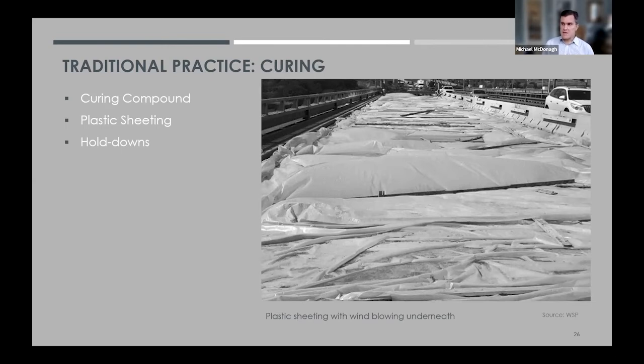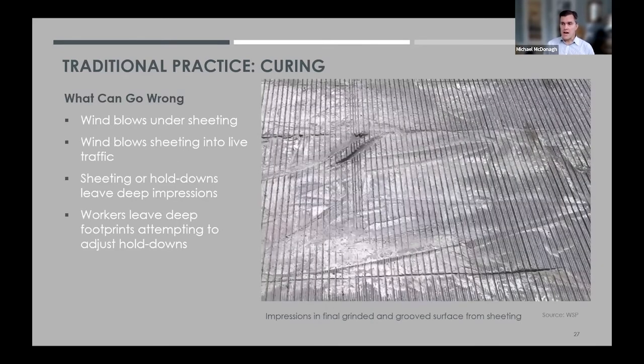The plastic sheeting needs to be held down, and that has to be carefully done in the early days or early hours when the UHPC is still soft. Contractors will often spray water on the sheeting until it hardens up, and then come back with plywood or 2x4s, such as you see in this photo here. You also see in this photo, wind is blowing underneath the plastic sheeting, which creates issues.